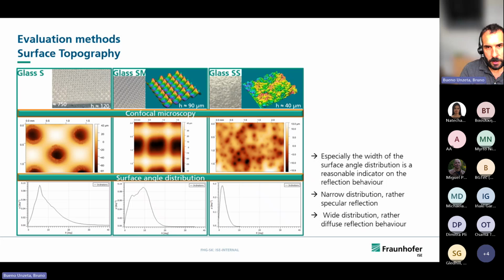So we move to the second evaluation method, surface topography. Based on confocal microscopy, we can analyze the structure of different glazings. Here I just define them as S, SM, and SS. What is interesting is to derive the surface angle distribution, because it gives us a feeling of the reflection behavior. If we have a narrow distribution, we can conclude that it has a specular reflection, so it can be glary. If it has a wide distribution, so different slopes are present in the structure, then we can assume that the reflection will be more diffuse.